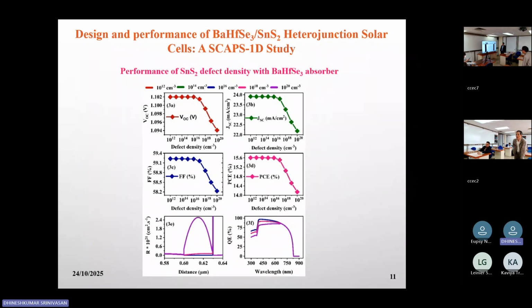In this case, Professor, the vacancies of sulfur and tin create the trap states that promote non-radiative recombination, Professor. The sulfur vacancy donates electrons, the tin vacancy traps holes, and the interface introduces additional mid-gap states, Professor. That's why lower defect densities give higher efficiency, and high defects can mean low efficiency, Professor.